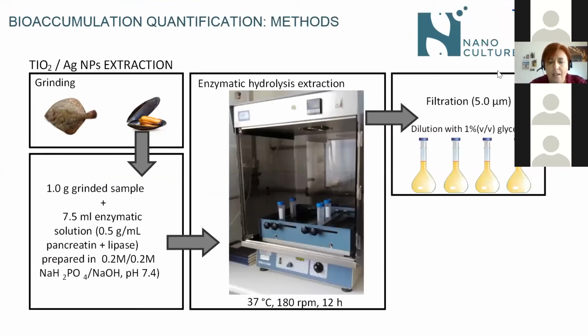Well, then we started to study the bioaccumulation, and we do it in different ways for quantification of the nanomaterials or the nanoparticles that are in the bodies of these aquaculture species. We had to perform first the extraction of the nanomaterials from the flesh of the turbot and the mussels and the seaweed. And as we want to know not the total content in metal, but the content in nanoparticle, we need to perform methods that will not destroy the nanoparticles in the process. And in order to do that, we need to perform soft digestion of the samples.